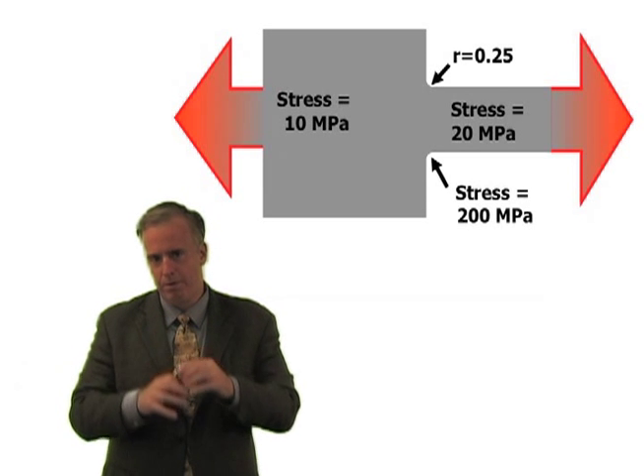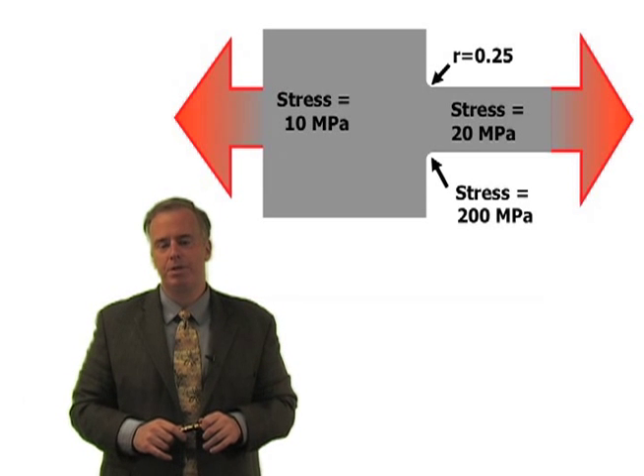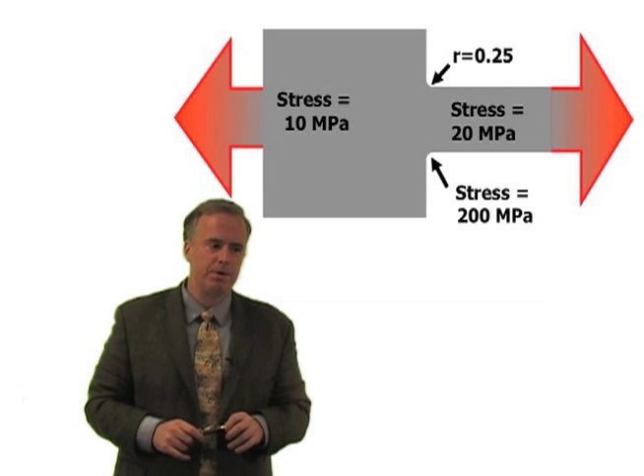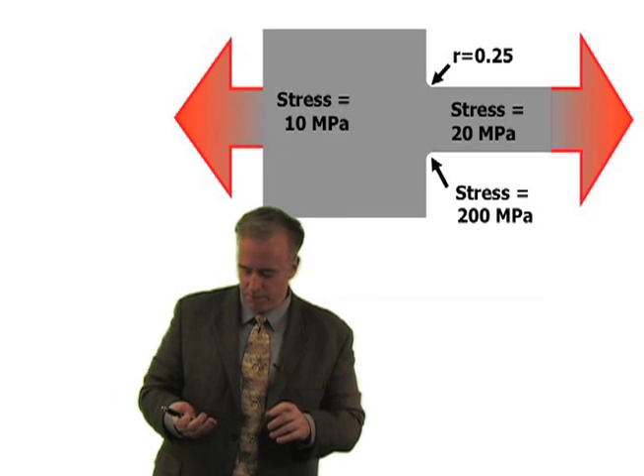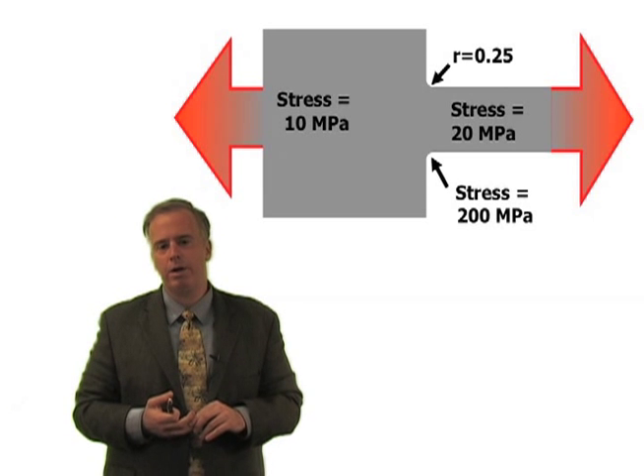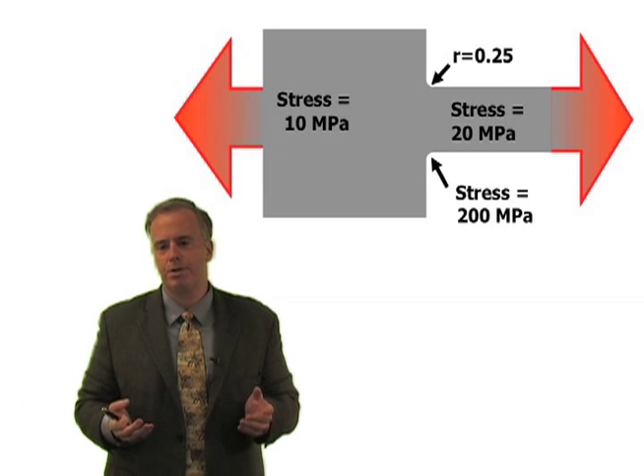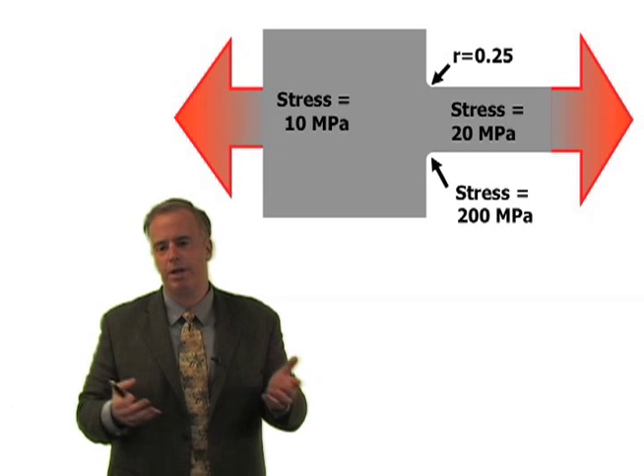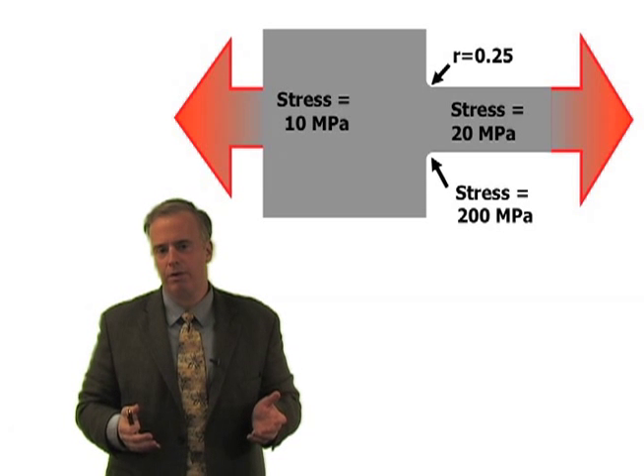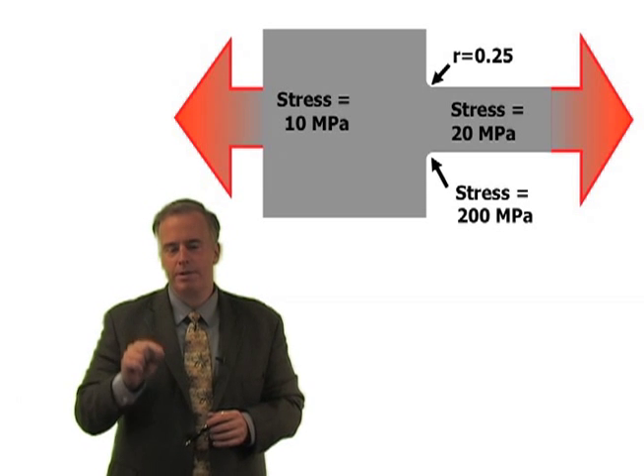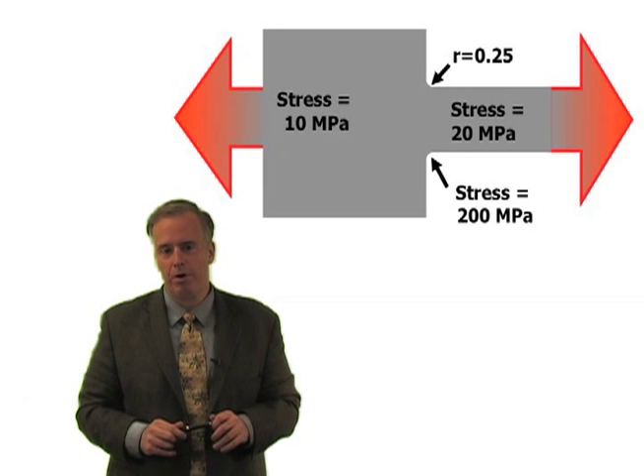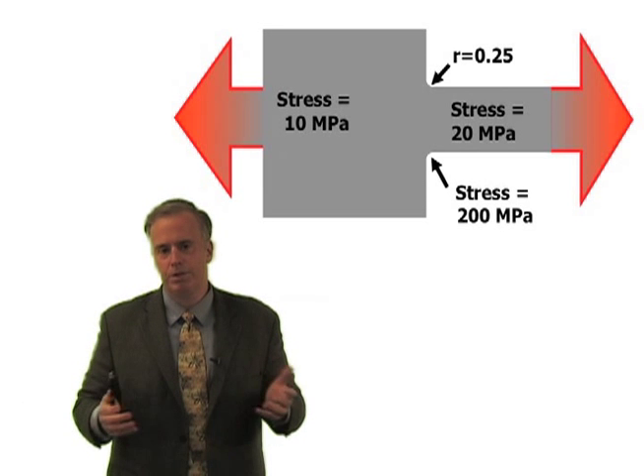If there's a very small radius in that part, those stresses are going to be much bigger. So with this particular company in India, I said I can work really hard to reduce the temperatures, help you with cooling, try to get the wheels sharper. We can do all these other things. But really, you've got to tell me what radius you have at that part and let's go measure it.